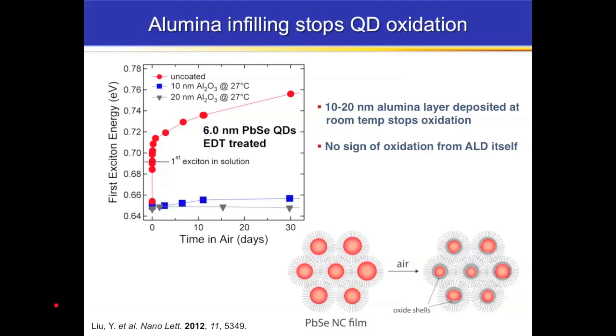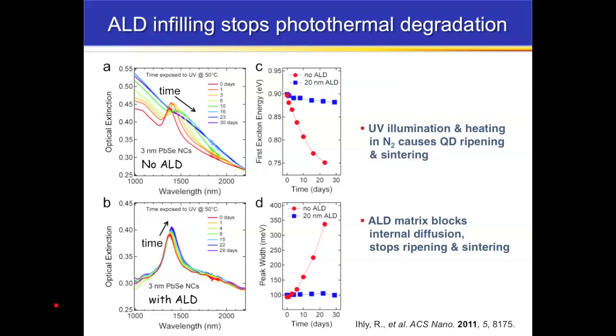If you just use, in this case, 20 nanometers of alumina at, say, 27 degrees C deposition temperature, you get absolutely no change in the first exciton feature with basically months and months of storage in air. And so it's a very effective oxidation barrier. It also stops internal degradation, what we call photothermal degradation.